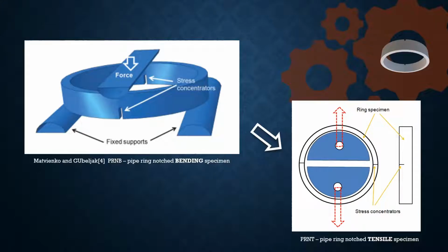In short, the PRNB specimen is a tubular ring loaded with bending, so a modified test procedure of standard SENB specimens was applied, where the fabrication of the specimens, determination of fracture mechanics parameters, and plastic limit loads are adapted to the cylindrical geometry. Making PRNB specimens is relatively simple, and in that way the same conditions are achieved in the area in front of the crack tip as in the pipe, e.g. residual stresses, degradation of materials due to exploitation, etc.